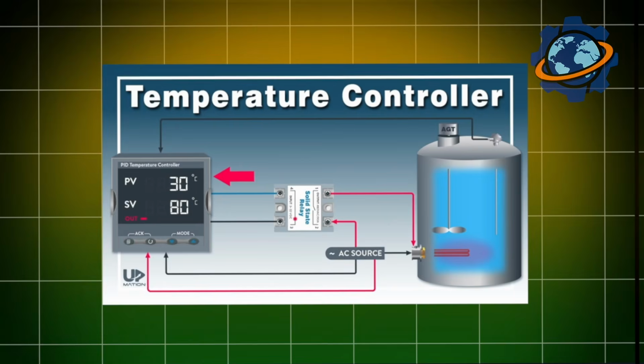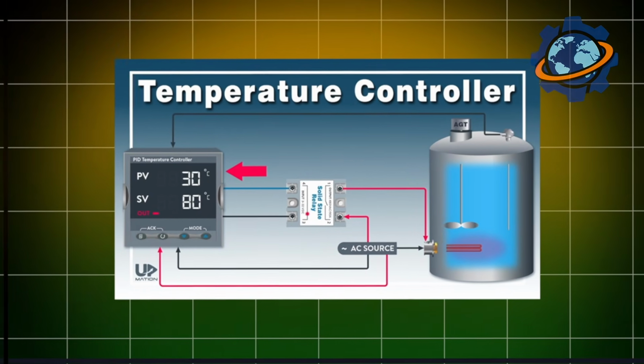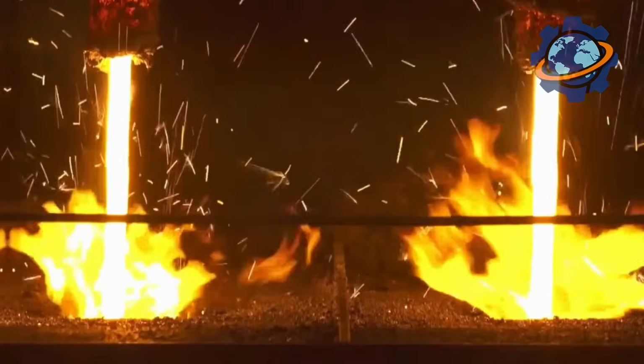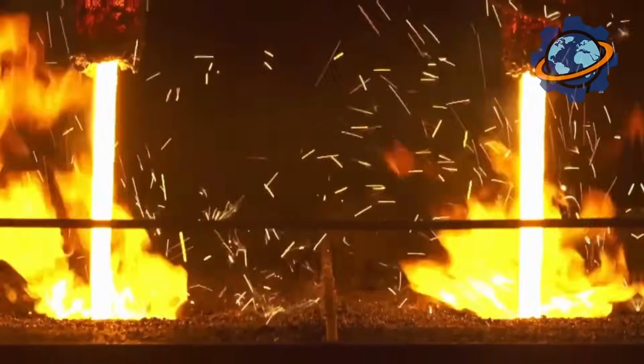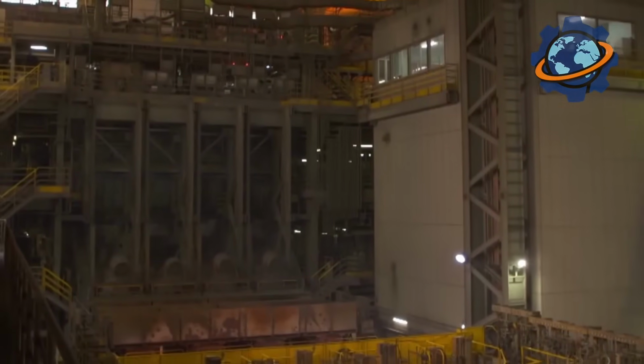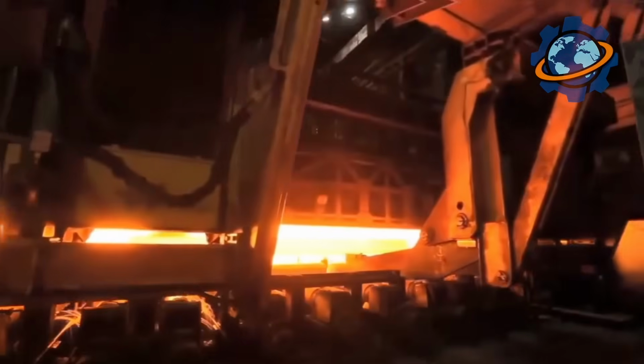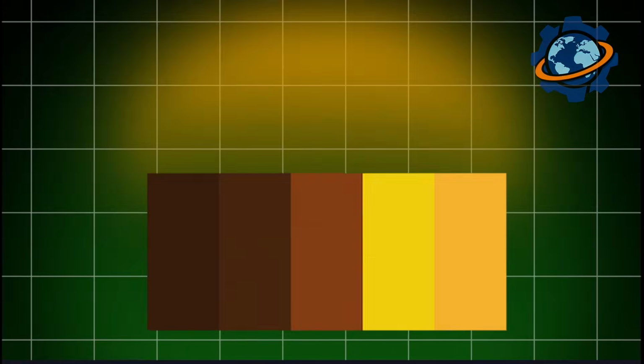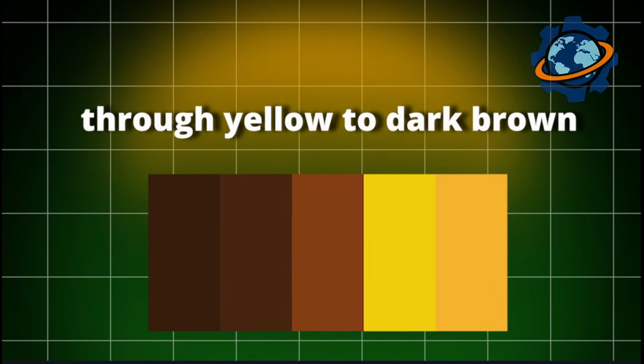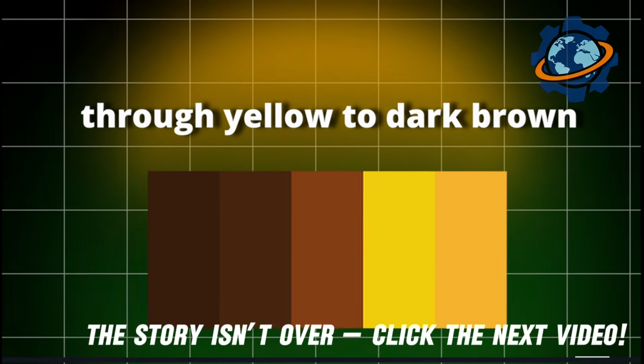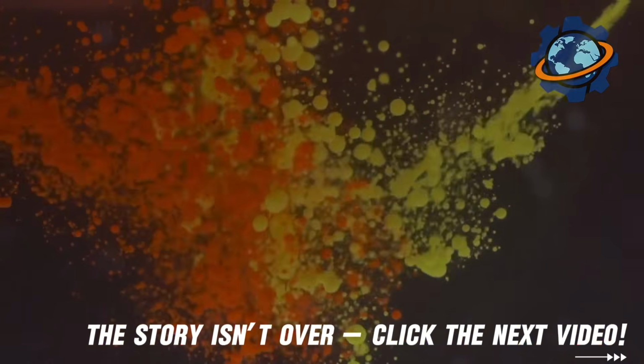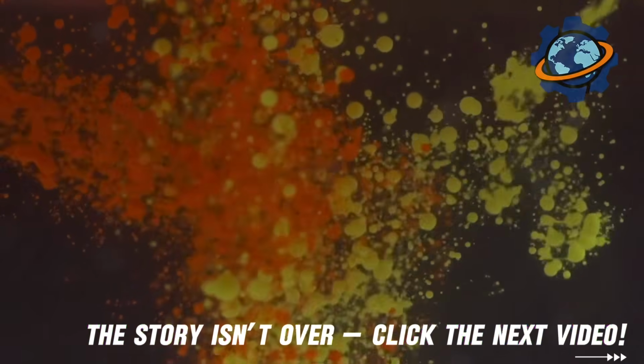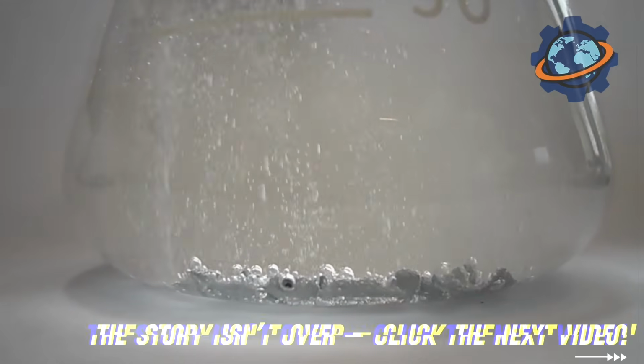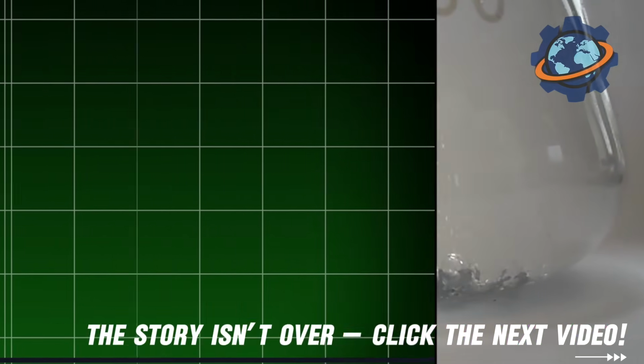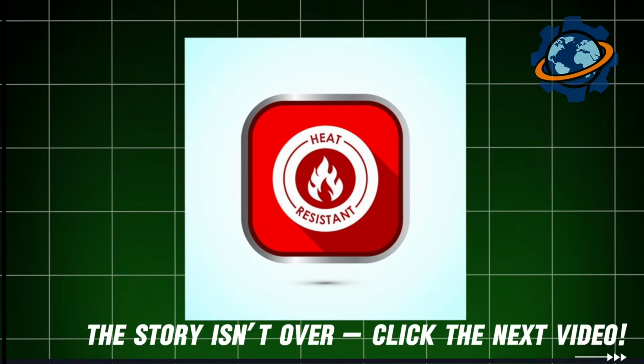Temperature control matters critically. Too hot, fibers ignite catastrophically. Too cold, cross-linking remains incomplete, causing failure during subsequent heating. The oxidation chamber maintains oxygen concentration at 23% with tolerance of 0.5%. Operators monitor fiber color constantly, watching white PAN transform through yellow to dark brown. That color change represents chemical metamorphosis. Polymer becoming something fundamentally different, no longer meltable, now heat-resistant enough to survive temperatures that vaporize aluminum.